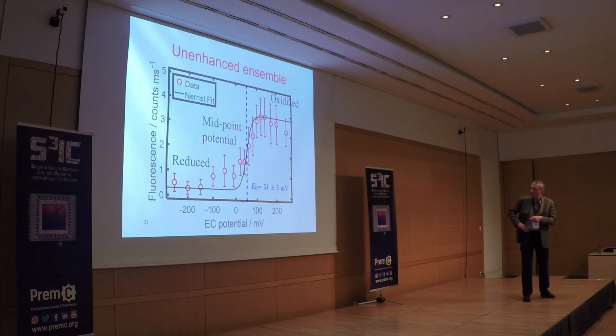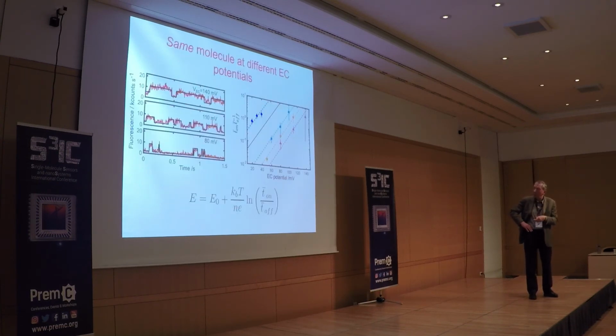Yeah, so that's a sketch of the ensemble measurement. This is done, of course, with an ensemble of molecules on a long time scale. And what you see here is just the fluorescence intensity. So here we don't have the statistics of single molecules, just the average, right? So the average goes up in a normal way. That's a Nernst equation fit. And if you look at this, for each of these molecules, this is one experiment. These were very lengthy measurements. So for this molecule, you stabilize the voltage at these values. We chose these voltages, and we measure all the molecules at a particular voltage, for example, 80 millivolts, right? But of course on different runs, so 80 and 100. And it was measured in this window between 0 and 140. Now don't ask me whether this is with respect to the standard calomel electrode or another electrode, I don't remember. But this is exactly the voltage you need to get this equilibrium in methylene blue.